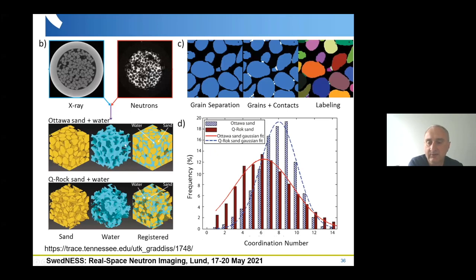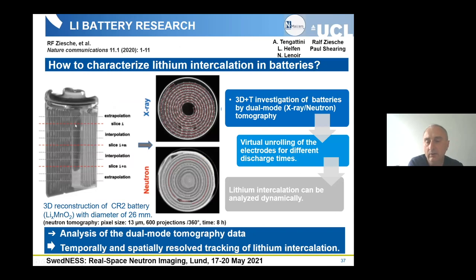So combining the X-rays and neutrons, it is possible to perform some statistical study and see, for example, the coordination number for the neighbors of each sand grain. We can see the water or the areas of contacts, and also estimate the amount of water or where the water is present. A single tomography using neutrons or X-rays would not really be able to capture this system in such detail.